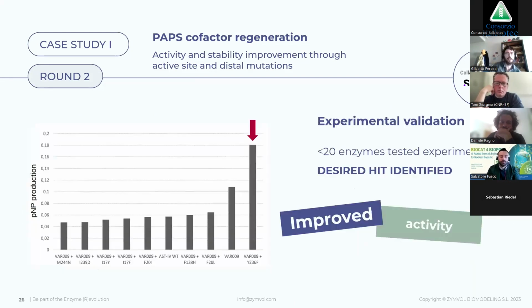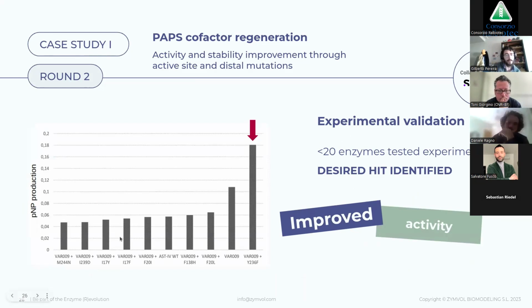It turns out that we actually improved quite a lot with respect to the original enzyme. So here you have the PNP production rate for AST4 wild type. Some of our double mutants didn't work very nicely, as you can see. Some of them were comparable, but we found one that was much more active.